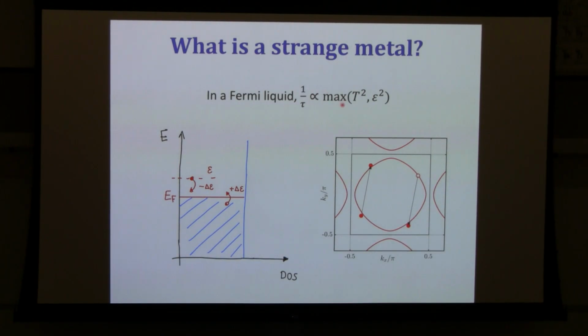Okay, now we ask, where would deviations from this behavior come from? For instance, where would a linear in epsilon and linear in T scattering rate come from? Okay, and this gives us a hint. To get a scattering rate which is parametrically larger than what we get in a Fermi liquid, we must have some pileup of low energy states that would provide this anomalously large scattering rate at low energies. Okay, and this is really the key of the matter. We have to identify what's the source of this high density of low energy states in the system that are providing the extra scattering. Okay, and these extra states don't have to be anything very exotic.